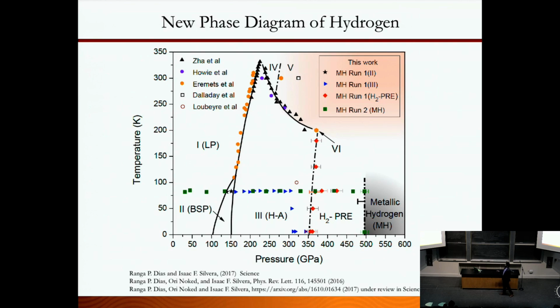If I summarize the hydrogen part right here, what you're seeing is a new phase diagram of hydrogen at low pressure, low temperatures and higher pressures, up to 360 GPa. Here you have the phase 2 to phase 3 phase line, and this is phase 1 to phase 2, at higher temperature. This is the measurement done by European groups, the German Max Planck group and the University of Edinburgh group. This is the phase transition from phase 3 to phase 4, and people have been seeing some new phase transition recently around phase 5, but this has to be confirmed.